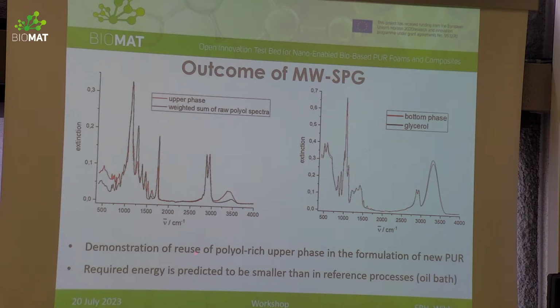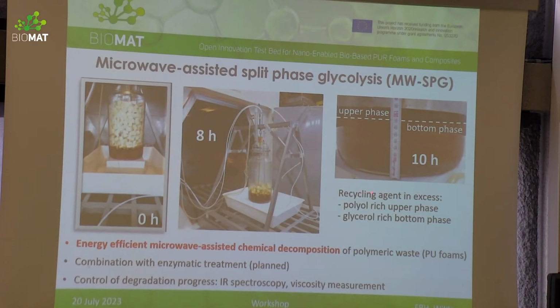Of course, the point why we are doing this is we intend to be more energy efficient than a standard process. As you can see here, we have now installed one 30-liter reactor in the middle segment of the Hephaestus oven. We have still place for installing 2 further reactors, and so if we get such a high degree of filling of the oven chamber, then we could estimate that at the end the energy balance of this microwave-assisted process would be better than that of a conventional process.